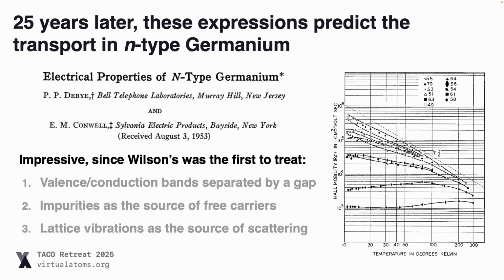Wilson's work was actually the first time that valence and conduction bands had been modeled as separated by a gap. It was the first work to think about impurities as the source of free carriers and lattice vibrations as the source of scattering in these semiconducting materials. And the results did very nicely and predicted some experimental trends.